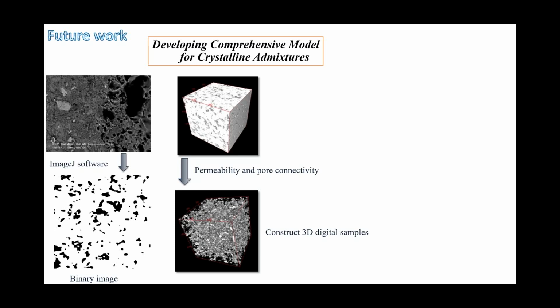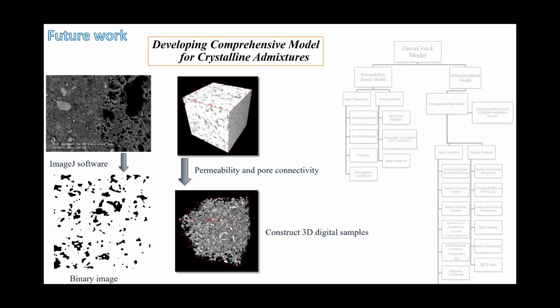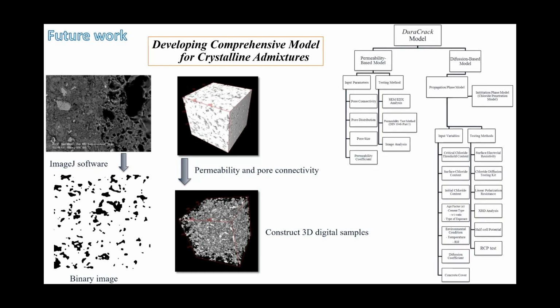And also for the field samples, for the columns, I'm trying to develop a model which I call DuraCrack, because this model is going to be helpful for concrete that has cracks, and it includes the self-healing process in the crack. When you have self-healing inside, there's no need to consider larger crack widths, because you can account for that natural phenomenon and also the one that we are engineering inside, to have less effort for the repair of those materials.